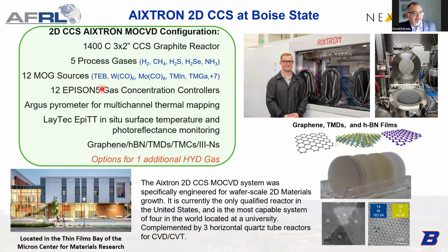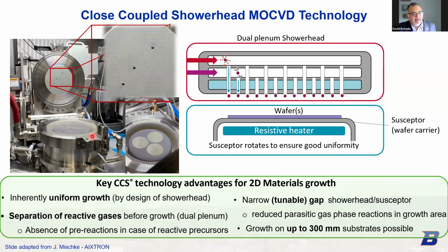Each of these channels has a EPISON 5 gas concentration controller. It is equipped with an Argus pyrometer to do kind of the multi-channel thermal mapping, look at the wafer surface temperature with the LayTec EpiTT as well. And so we can control the process based on gas concentrations and the wafer temperature, right? We do have photoreflectance, I should say, sorry. The EpiTT can also measure the photoreflectance of the sample for controlling the process.